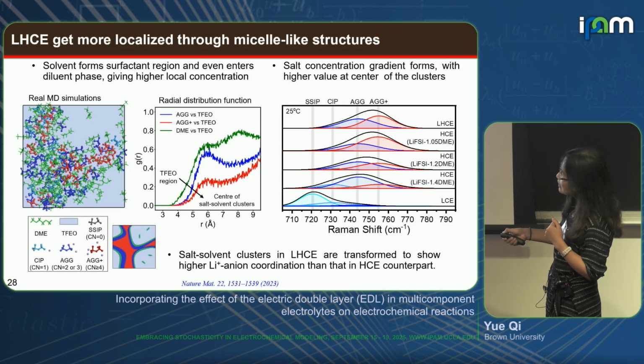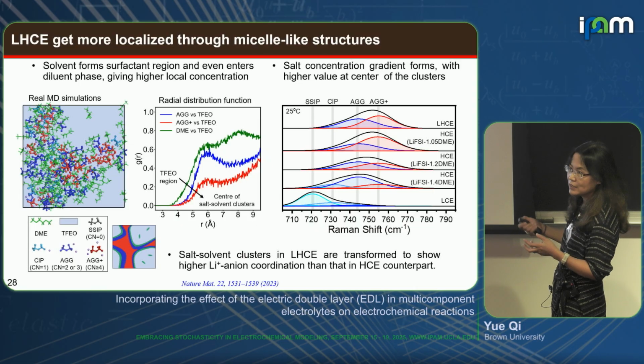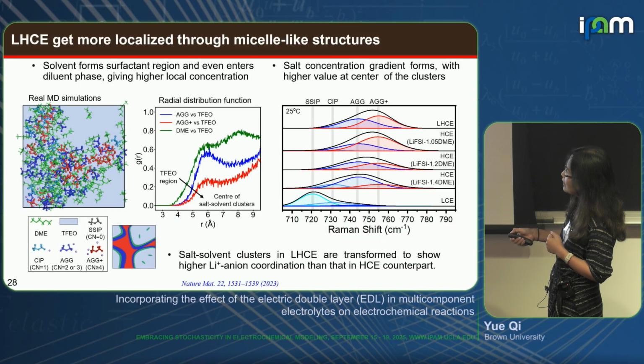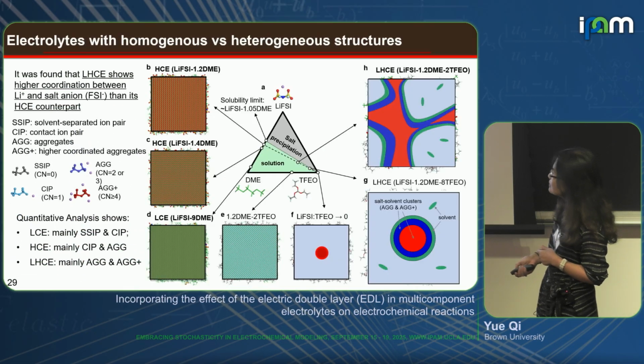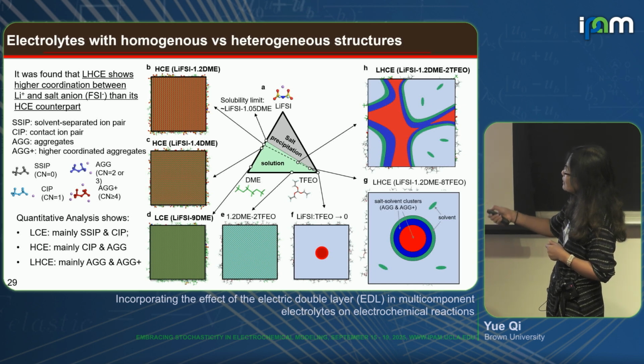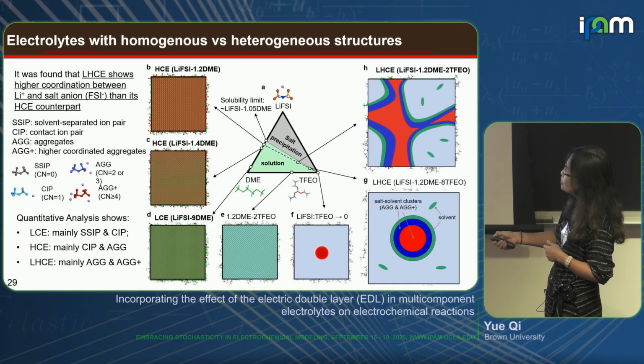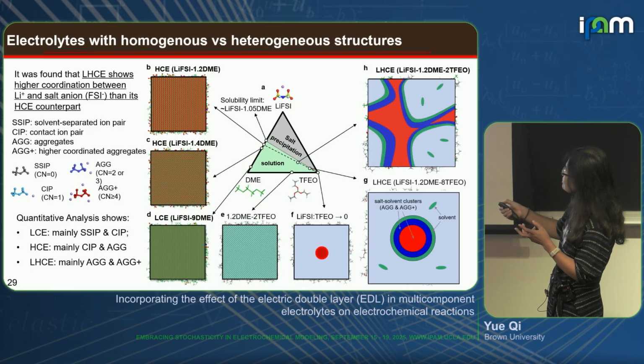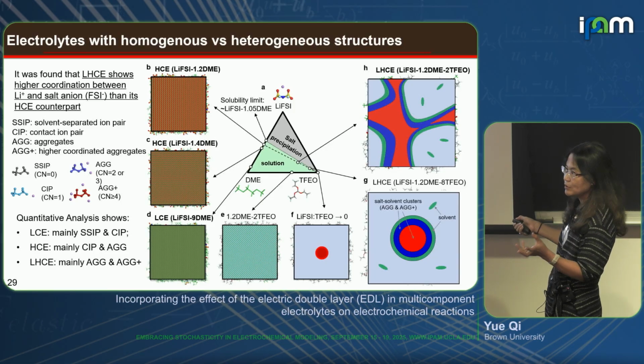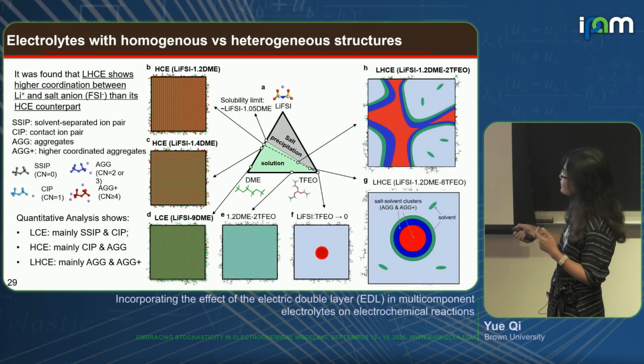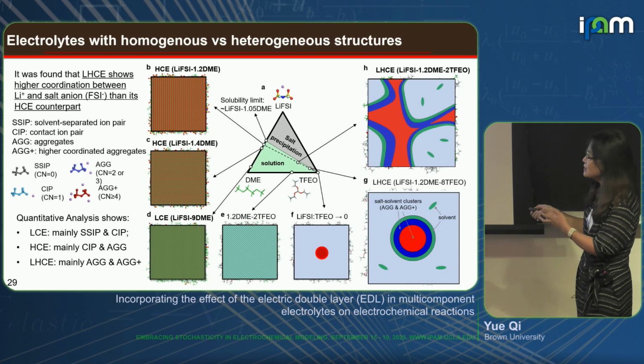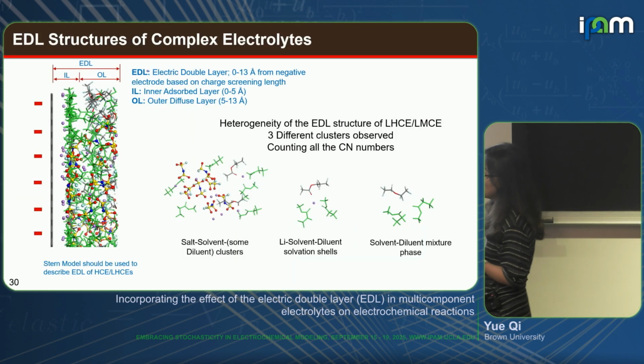And then we do our MD, and if we go inside this cluster, we see a higher percentage of AGG plus, that's the aggregates, right? And you can also understand why you will have such a concentration gradient inside this salt-solvent cluster. So this is a schematic to show that traditionally we've been thinking about electrolyte as homogeneous, from very dilute to higher concentration, but still homogeneous. But this new localized high concentration electrolyte is a ternary electrolyte with a nanoscale, micelle-like structure. Depending on concentration you can have isolated or network. And we convinced the Nature Materials editor this is a material. It's not so much chemistry, but a really nanoscale structure, right?